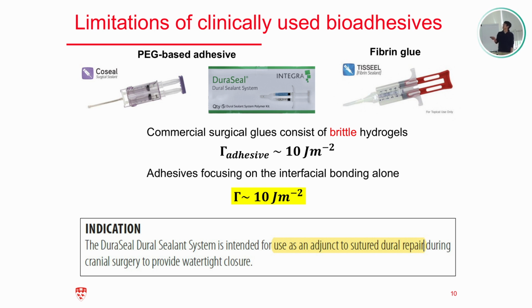So here is a slide presenting the limitations of these clinically used bioadhesives. Examples include the polyethylene glycol hydrogel-based bioadhesive or the fibrin clot-based bioadhesive. If you test their mechanical property, you realize this kind of gel is very brittle. To tear this kind of gel, you only need about 10 joules per meter squared of energy. And if you measure the adhesion of this surgical glue on biological tissue, you end up with a very low adhesion energy, again on the order of 10 joules per meter squared.